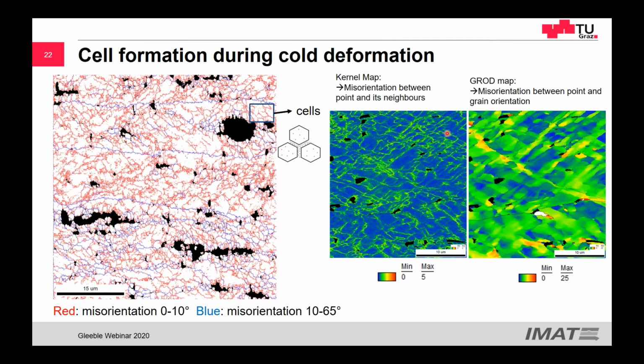And you can see also that close to some big particles, the aluminium alloys from the industry are, let's say, a bit dirty. They have these iron aluminides, formed with silicon, and they also produce some kind of further strengthening. And you can see close to these black particles, higher deformation zones. This could also have then later an effect on the recrystallization.